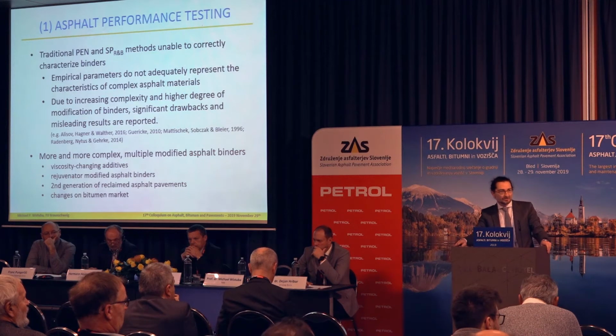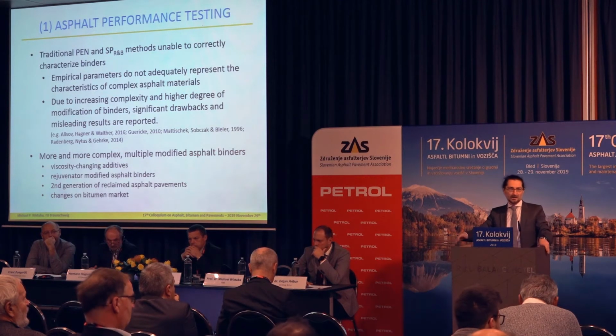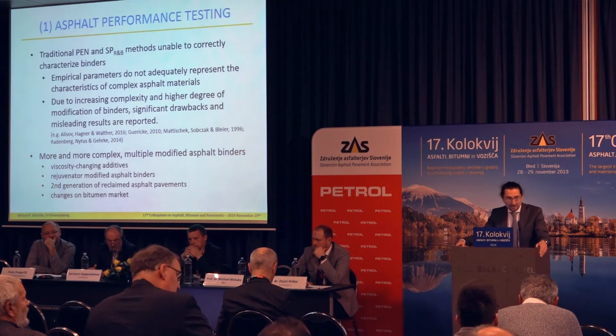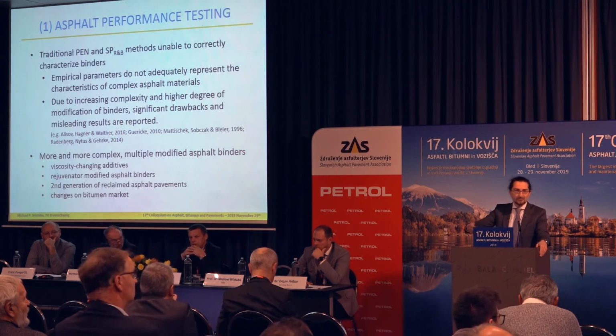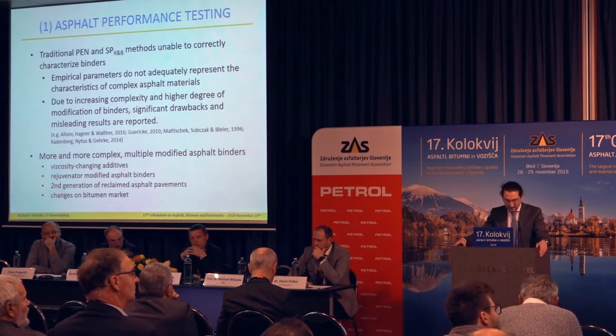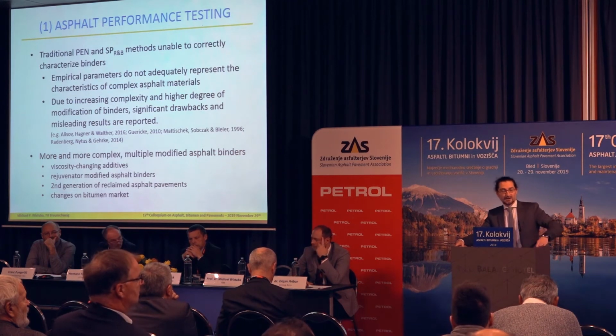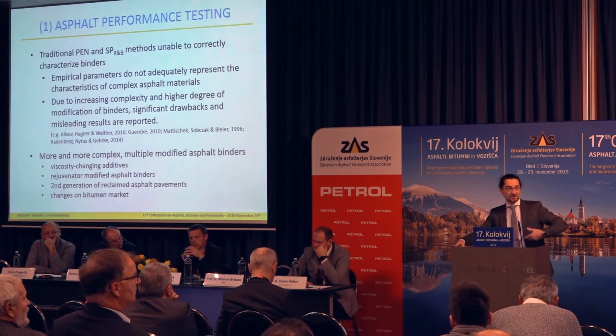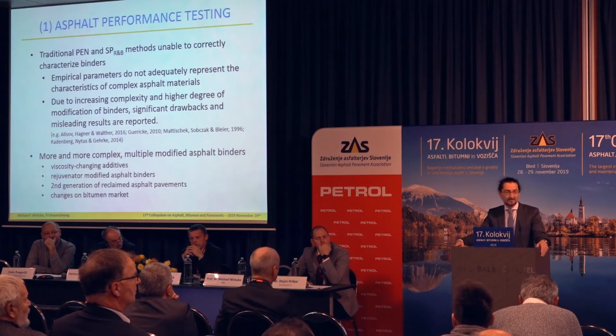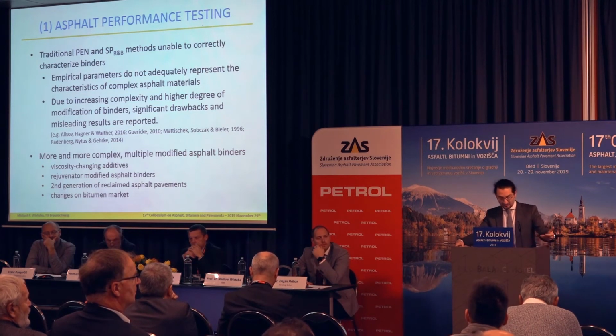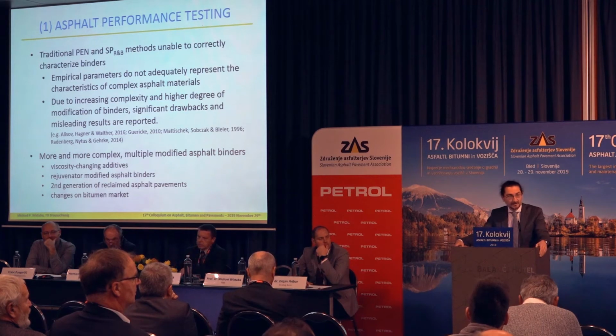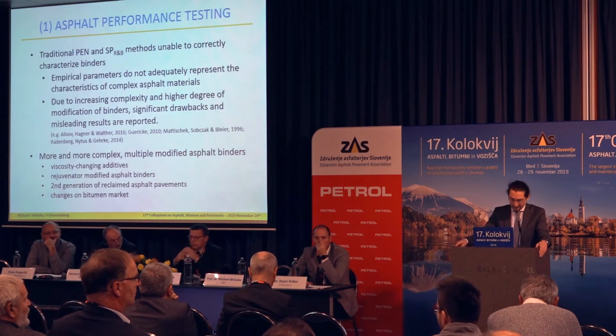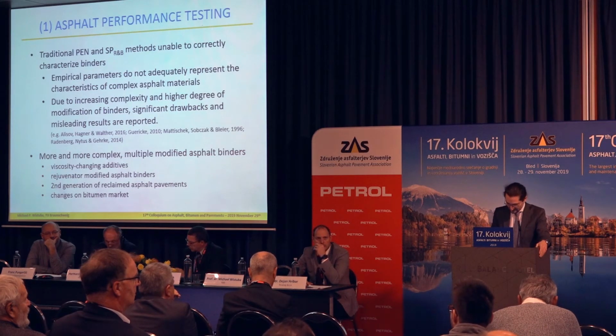We are using viscosity changing additives to a high amount in Germany. We are using rejuvenators when we do recycling. So we are using not only fresh binders, we are using chemical products. And in some regions, like in northern Germany, we are already at the starting point of the second generation of recycling of asphalt. So the material is really highly modified. And of course, there you can observe changes on the bitumen market in the last 10, 15 years.